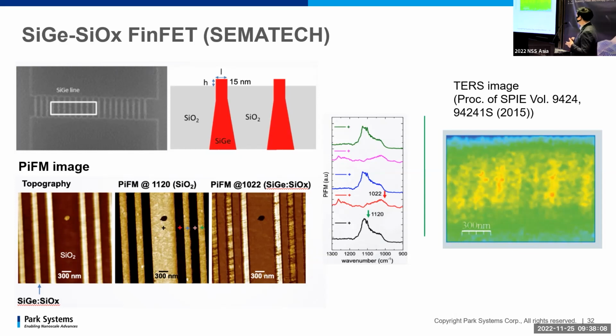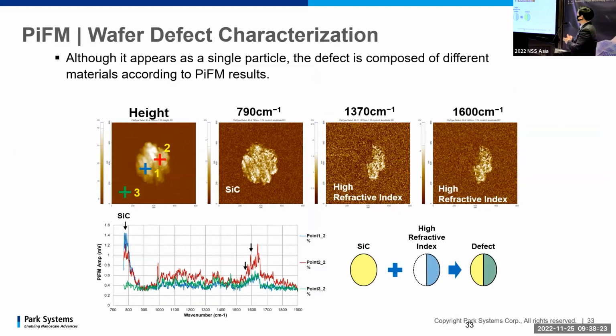And this is a comparison with TERS images, taking the same FinFET of silicon germanium and silicon oxide, and you can see which technique is better. When we look at a defect, we can identify the chemical identity of the defect. We first thought this must be a silicon carbide defect, and when we went through the 790 wave number for silicon carbide, it showed up. But later on, with a different wave number, we found that only half of the particles showed up. So in fact, it is not just silicon carbide.